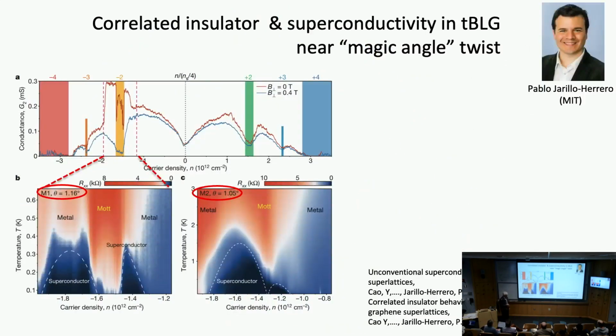So one more word about this before I tell you a little bit more about our own theoretical work. And this is again from the work of Pablo Jarillo-Herrero at MIT. This is again the situation of correlated insulator and superconductivity in twisted bilayer graphene near this special angle that produces these effects. So what you see here on the horizontal axis is the carrier density. That's the number of electrons in the system relative to the neutral system. 0 is the neutral system. So on this side you add some electrons, on this side you remove some electrons or you create some holes. On the vertical axis is the conductance, which you can equally well interpret as the density of states, the density of electronic states in the system. So you see this kind of behavior, this kind of humps, where the electronic density of states is.